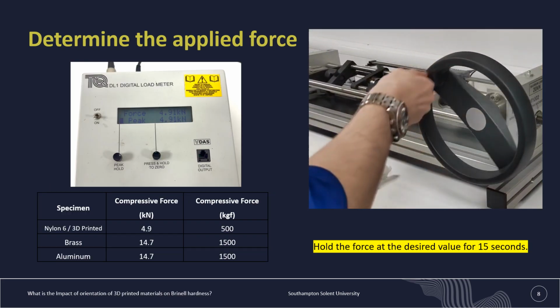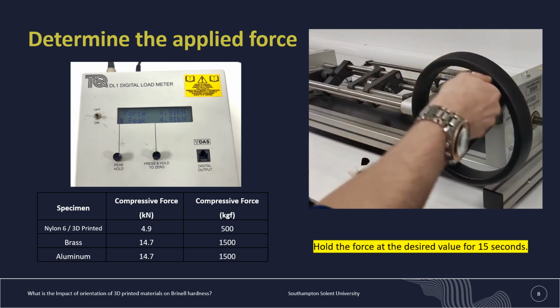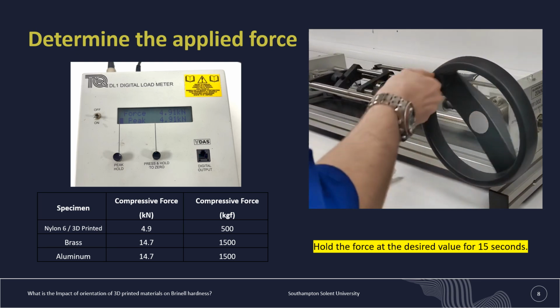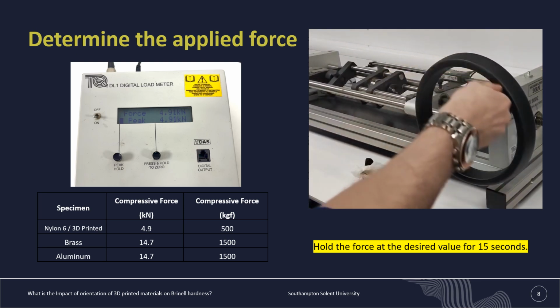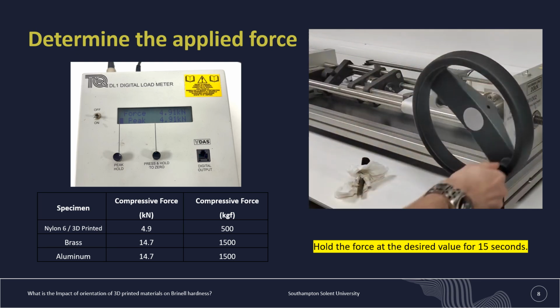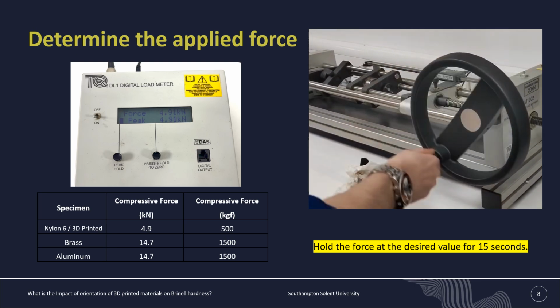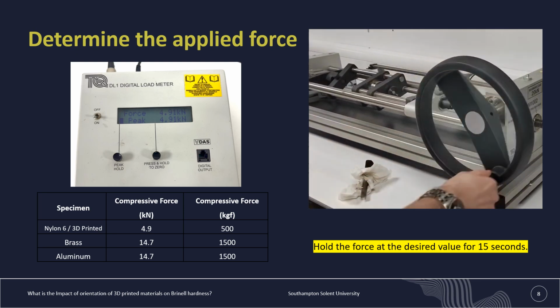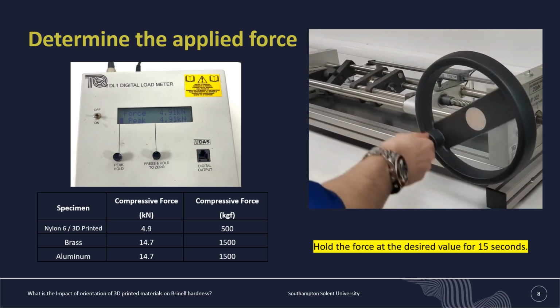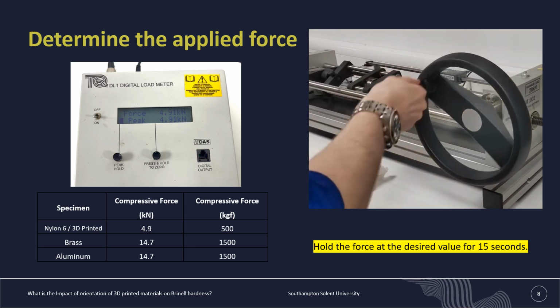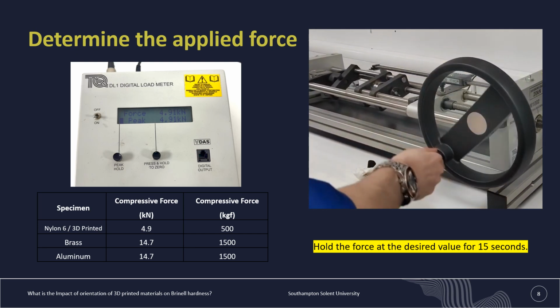We applied 4.9 kilonewtons of force to PLA, following the recommended value for nylon 6 from a user manual. The hand wheel was turned clockwise steadily until reaching this force, taking care since PLA is softer than metals. The force was held for 15 seconds to ensure accuracy and prevent force reduction.